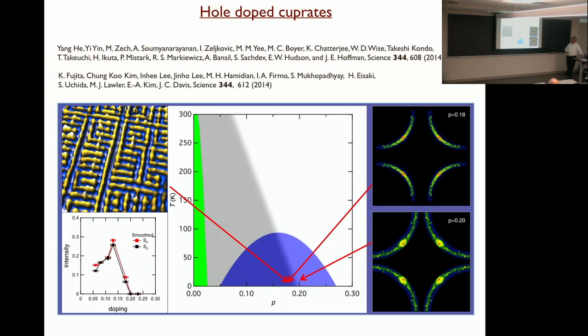I'll just show you some of the experiments. So for example, if you look at STM data, if you just look below this point, then you get this kind of picture for the dispersion of the electron near the Fermi level. But that, in fact, doesn't look like band theory for the simple reason that you never get arcs in band theory. They just seem to disappear to nothing. On the other hand, if you go just a little bit above, you see that you do get complete curves. So this curve would, in fact, be just a circle. So you get a very simple circular Fermi surface of holes. You see that clearly above this point.